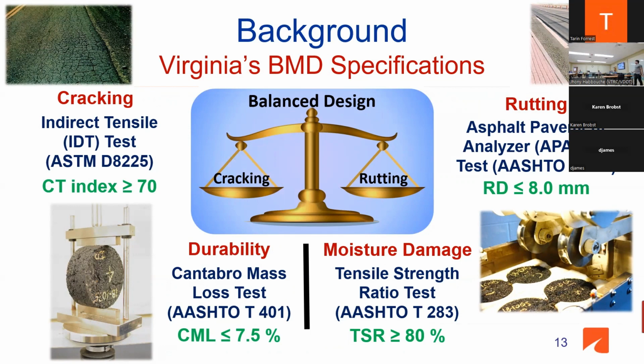Probably you've done some of that testing in your labs if you're in the asphalt mixture domain. And then we look for the cracking tolerance index, what we call CT index, with a minimum value of 70. So we project to have a good performing mix if it has a CT index of 70 and above.